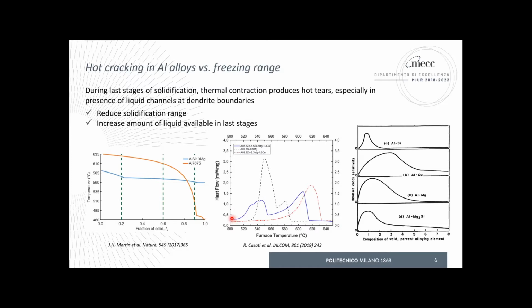What can we do? Let us try to mix these two compositions. It was a very preliminary job. Some years ago, we did that. We tried to mix those two powders, and we processed them by laser powder bed fusion according to a proper fraction. And the resulting curve, I was wrong. Sorry, the black line is for the aluminum, and again, aluminum silicon. We have primary aluminum and lots of eutectic.